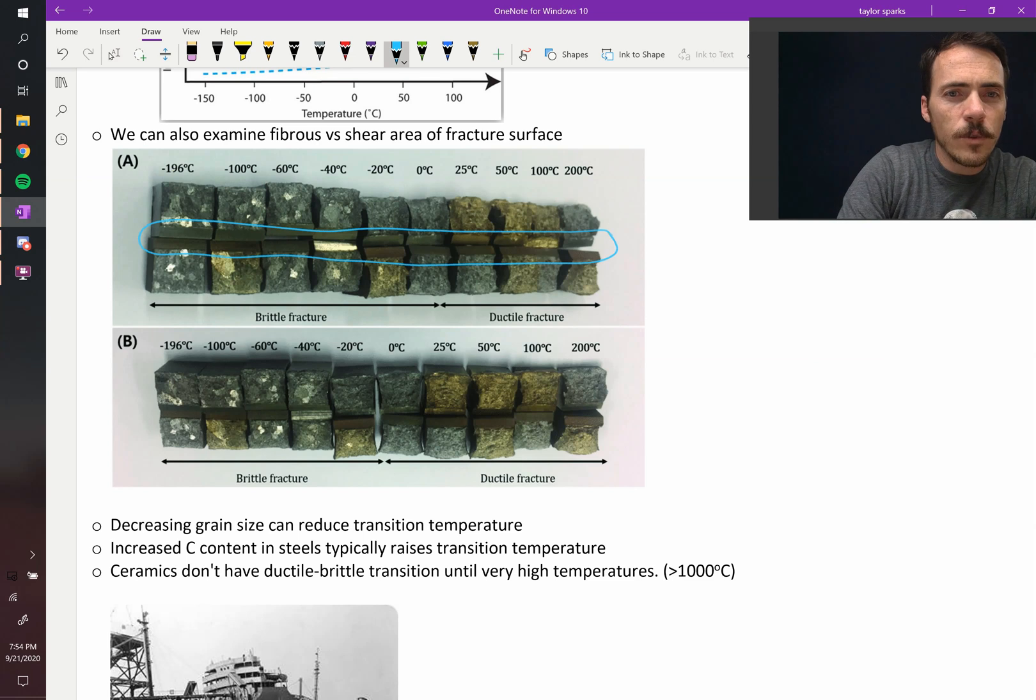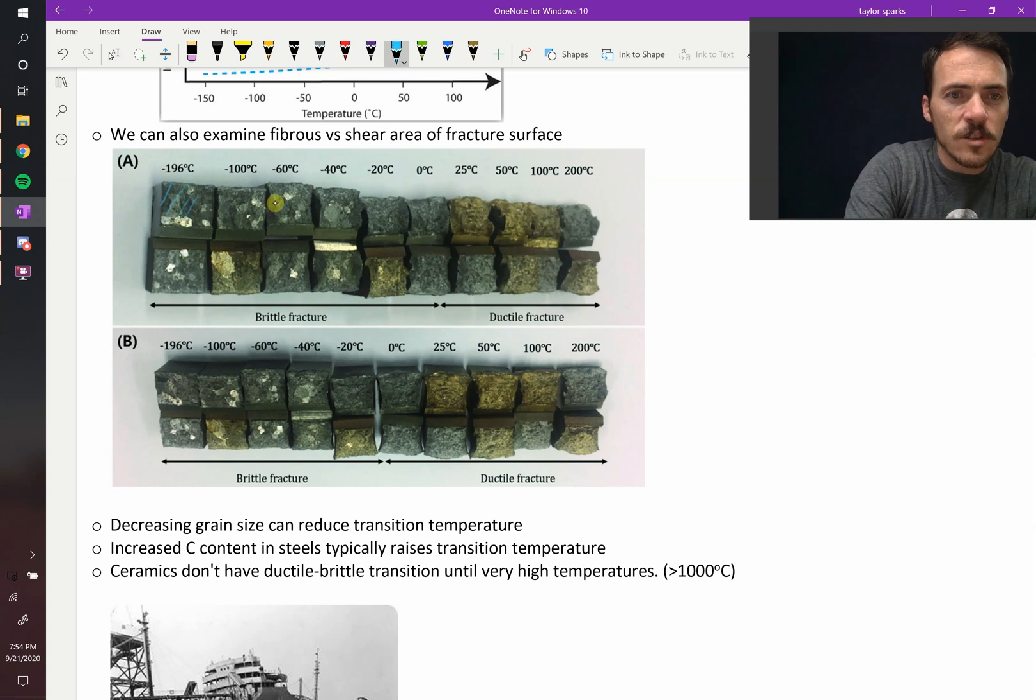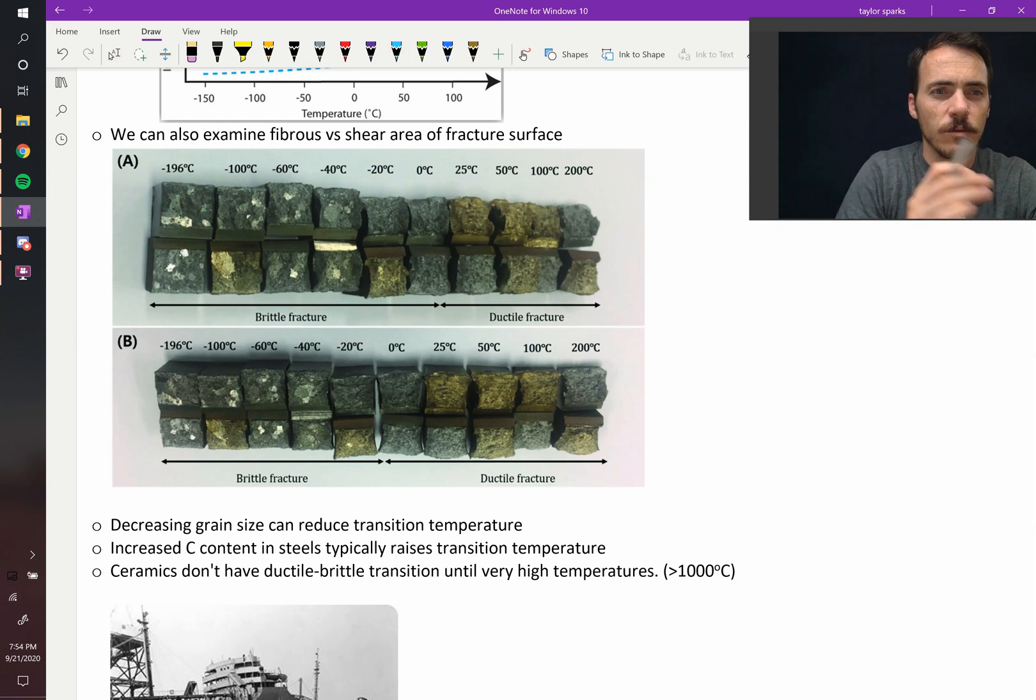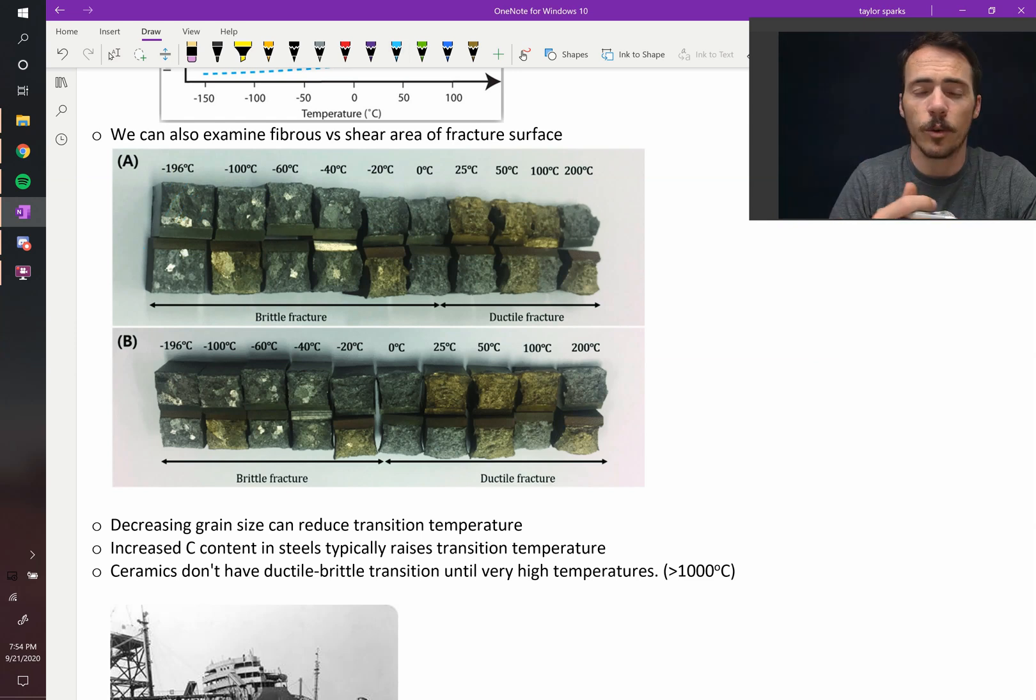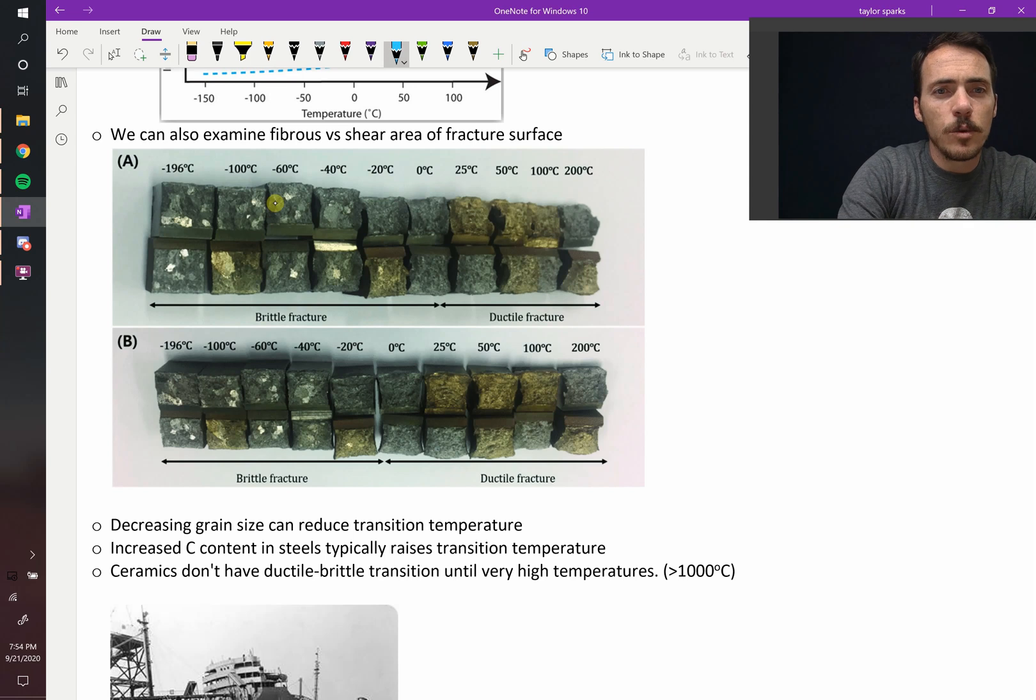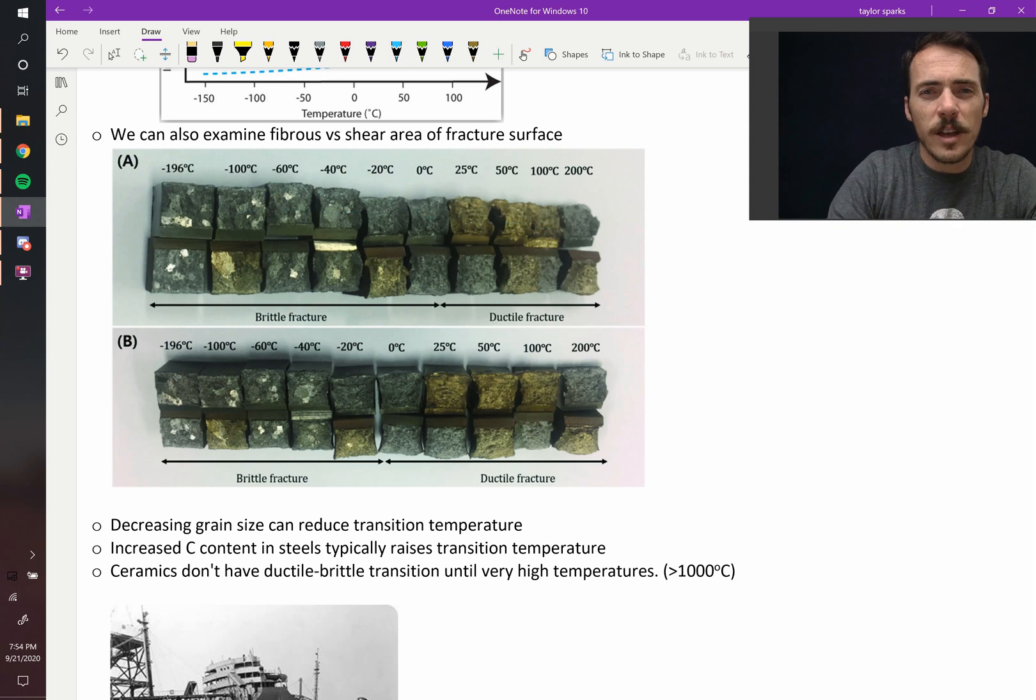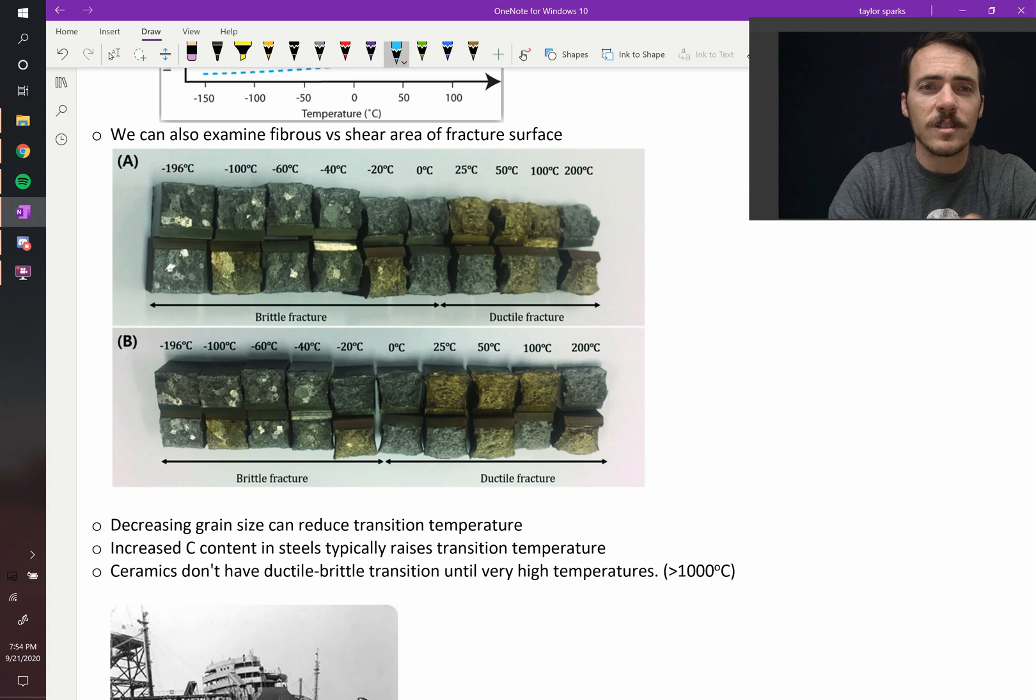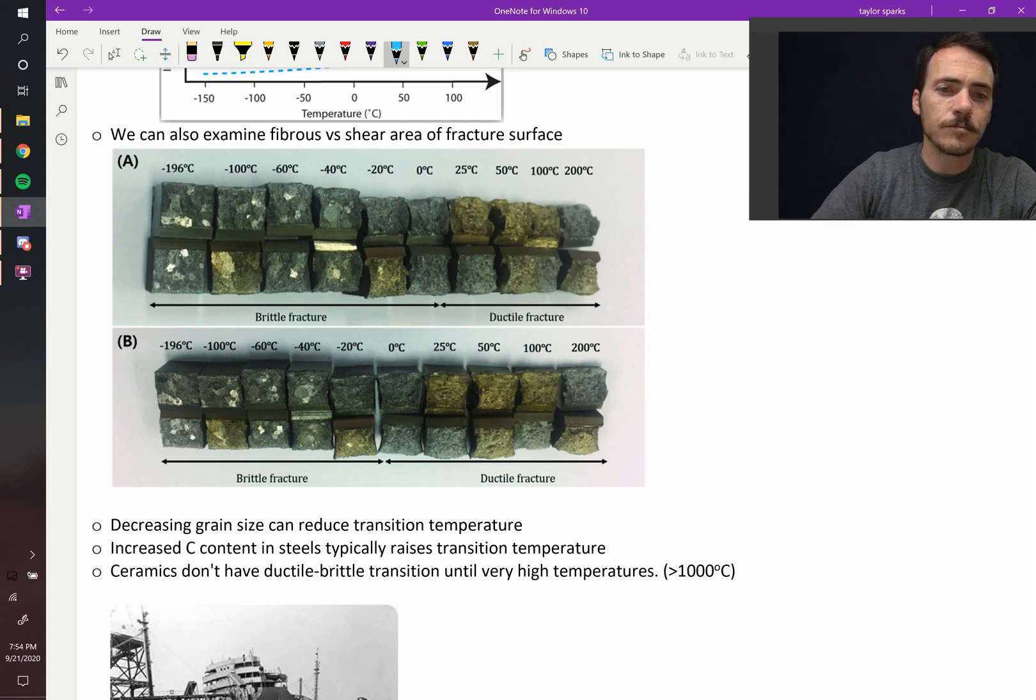But then from low temperatures, it's much more flat. You can see it's cleaving great big grains in half. Those different regions of different metallic luster are different grains of materials, different orientations. And then as you move to higher temperatures this way, you lose those grains. It becomes more crumbly and rough because it's deforming more. It's allowing much more deformation so you can see the transformation take place in that material.